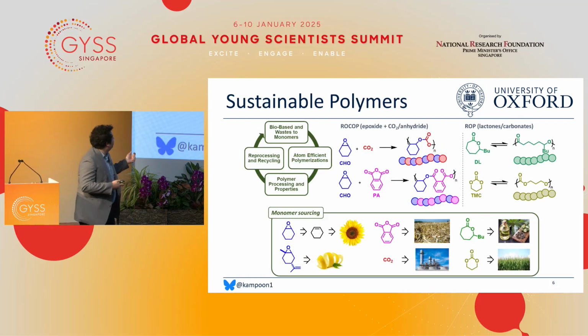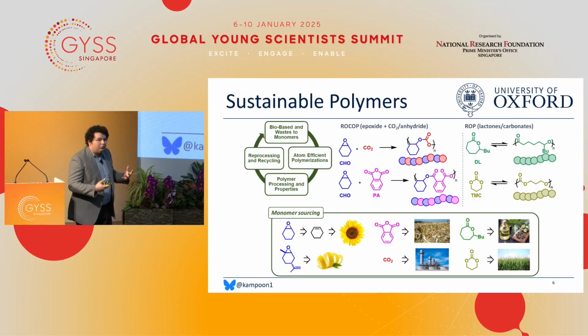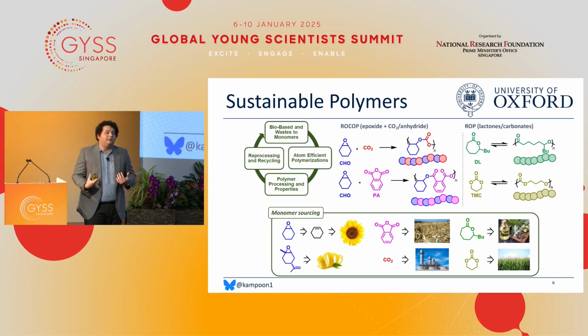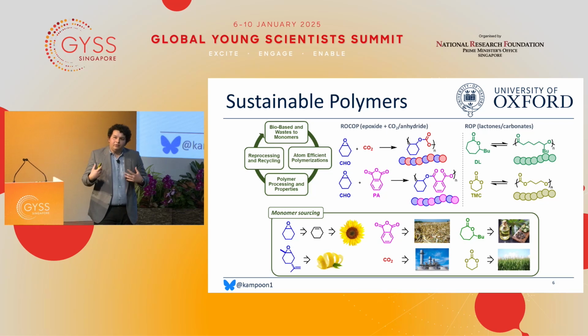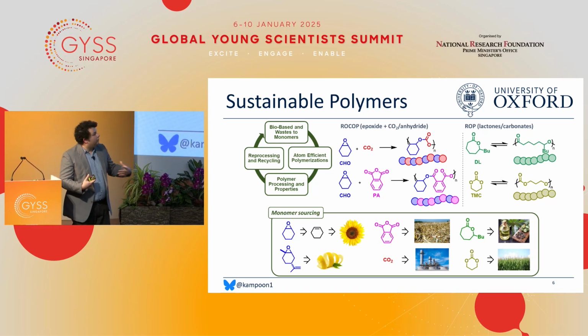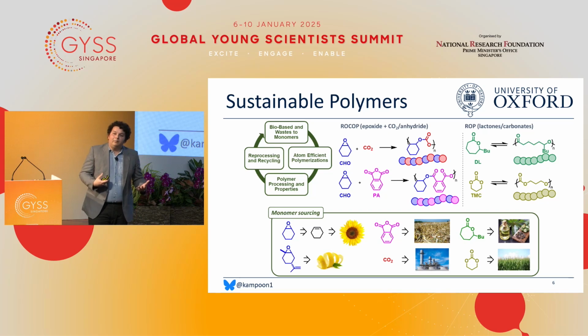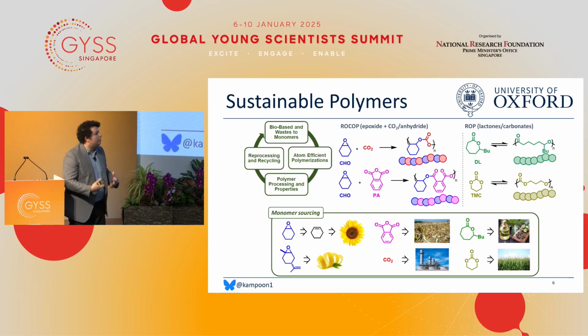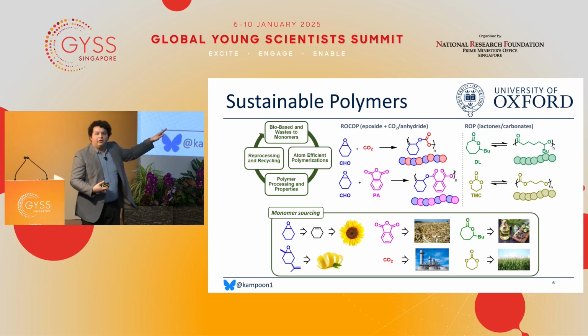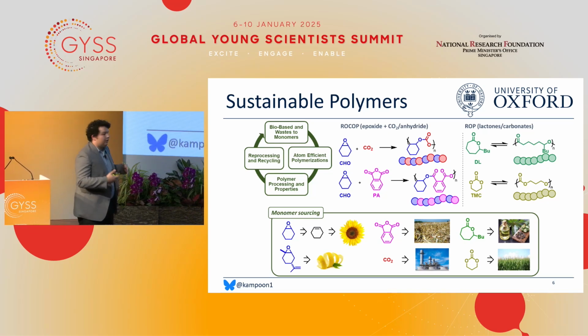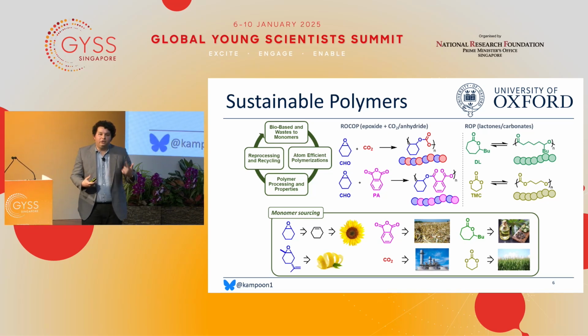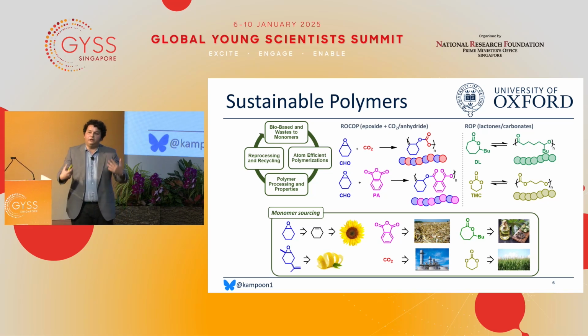In our group, we are particularly interested in trying to find sustainable alternatives to these. And we like to do this through a range of different polymerization techniques, but mostly through the ring opening polymerization or the ring opening copolymerization of monomers that can be derived from biomass, or in the case of my PhD and my research, looking at directly polymerizing carbon dioxide to form polycarbonates. Obviously, CO2 is a really attractive monomer. It's cheap, it's overly abundant, and if we find a way to utilize it, we can valorize it.